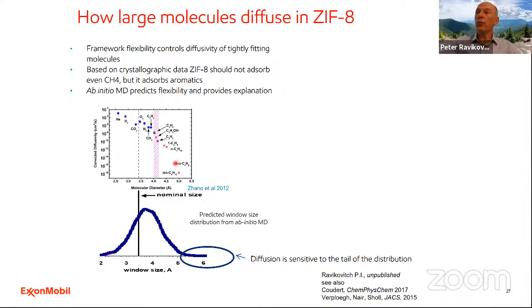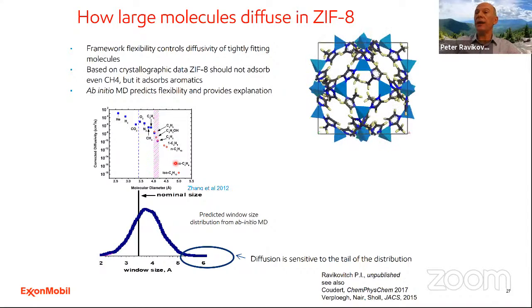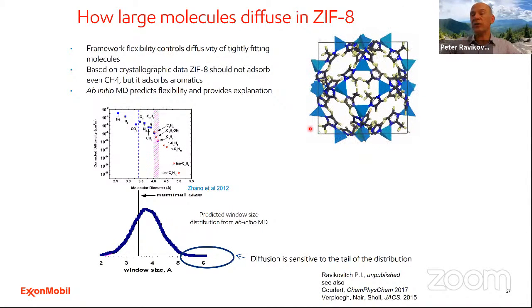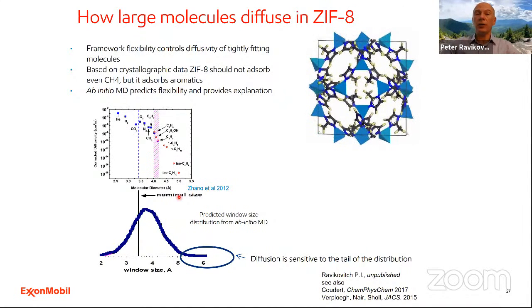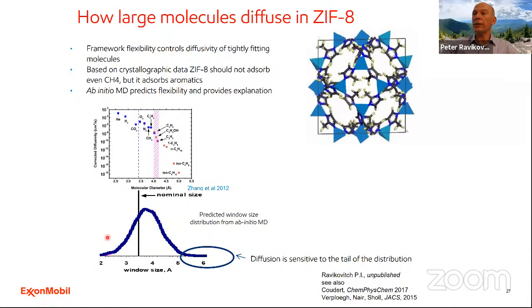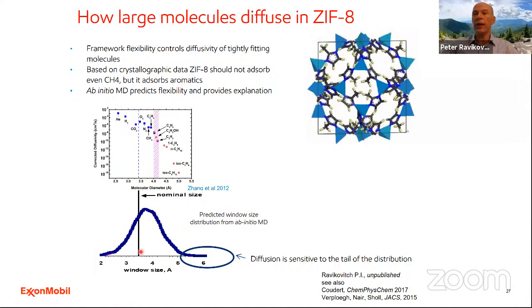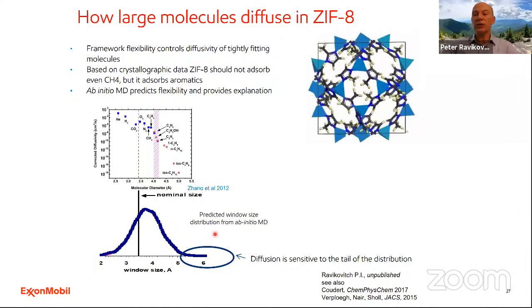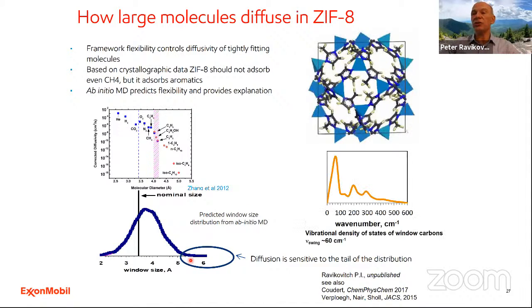So if you perform molecular dynamics, this is ab initio molecular dynamics simulations, you can plot the histogram of the window size distribution just for the empty structure. And as you can see, this distribution has a substantial tail. This tail tells you that at least sometimes the structure is substantially open for diffusion of other molecules. And as you can see, there is a frequency at which these vibrations occur.